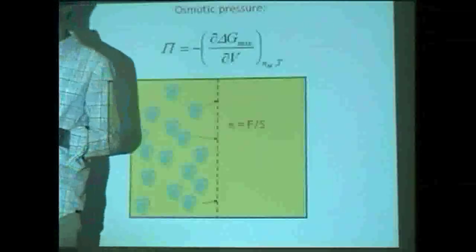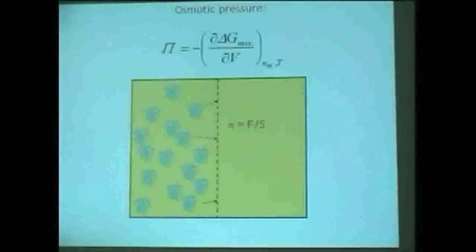So this is very pleasant to find out that we end up with this law when we are at very low polymer volume fraction. This is logical because whatever gas you take, if you decrease the concentration of the molecules inside the recipient, you will always end up with a law like this, because if you have very, very small amount of molecules, they don't see each other, and the volume that they occupy is negligible. Flory was probably very happy to find that, because it means that his approach is meaningful, physically acceptable.